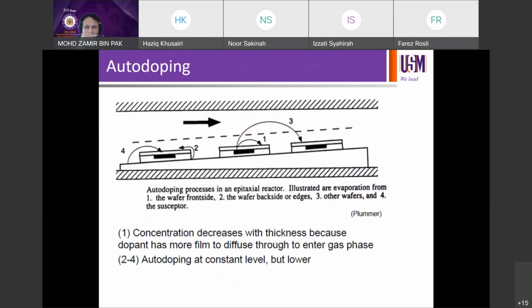I think we have this in for auto-doping. For example, auto-doping processes in epitaxial reactor. So you're running this process in a furnace, epitaxial furnace. Illustrated here are evaporation from number one wafer front side. Sebab this will be out diffused, and then you can actually auto-dope your front layer, or you can also auto-dope the neighboring substrate, neighboring film, because you have a gas stream coming in. So gas stream ni dia akan bawa, jadi carrier gas, dia akan bawa dopant evaporation, evaporated dopant if you like, into the atmosphere within the chamber, within the reactor, to auto-dope the next substrate. Okay, that's possible.